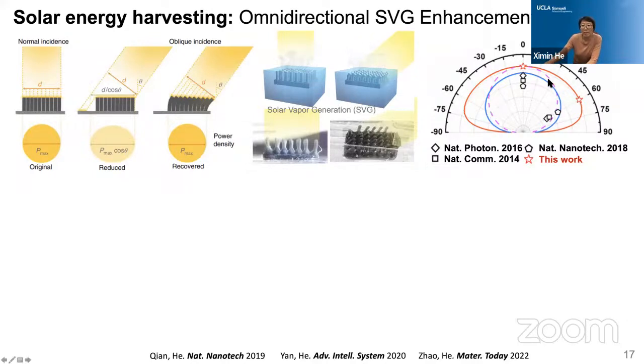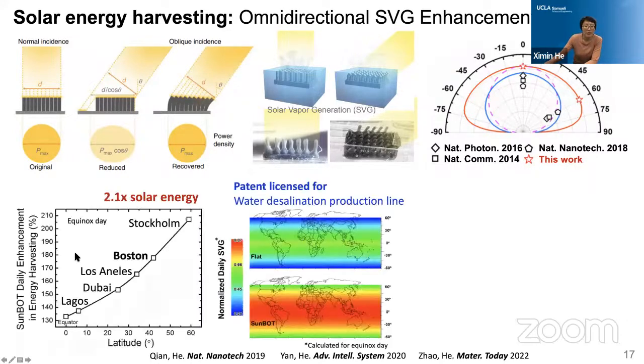So by comparing this light tracking surface with other non-tracking surfaces reported in other works, we found, especially at a large incident angle, this tracking surface can harvest more solar energy and produce more water than the non-tracking surface. At 60-degree illumination, you can harvest about 4 times the water compared to the non-tracking. And imagining if we apply this material at different latitudes in the world, then you may have a